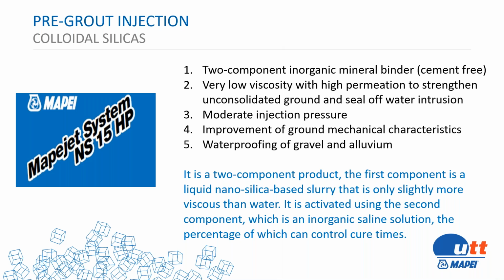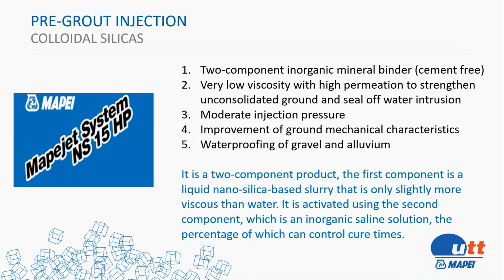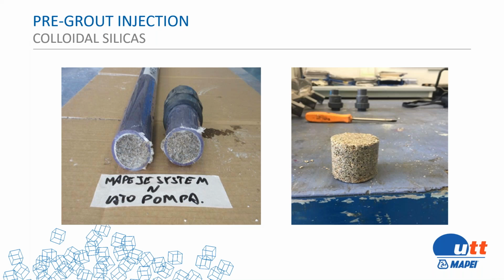Next slide. We make the Mapejet system NS right here in America. And with this division of the Mapejet system, we have one that takes about 3 hours to cure, so it can permeate the matrix of the soil. We also have the availability of increasing the reaction time down to even seconds. So the idea is that we have this low viscosity material, and in this slide you can see how under pressure it can permeate through even fine sandy dolomite soil and create a very, very solid matrix.